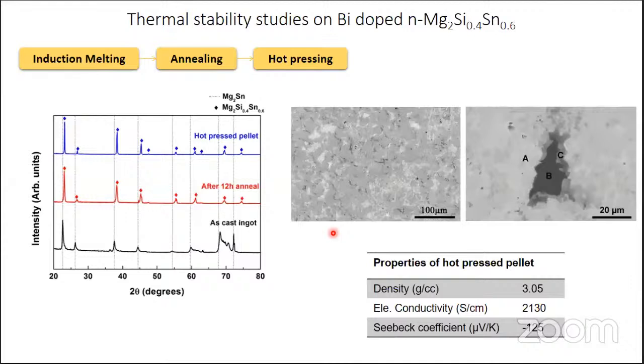But the critical aspect here is magnesium, because in metallurgy there is something called the Ellingham diagram. It gives the oxidation tendency of all materials. If you see in the periodic table, magnesium's oxidation tendency is even more than lithium. It's extremely difficult to prevent it from oxidation. The processing and melting, all these things, we have to do in an extremely controlled inert gas atmosphere or a slag-covered atmosphere to make the compound.